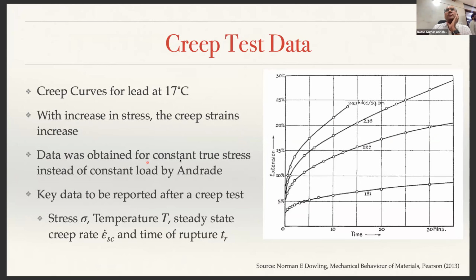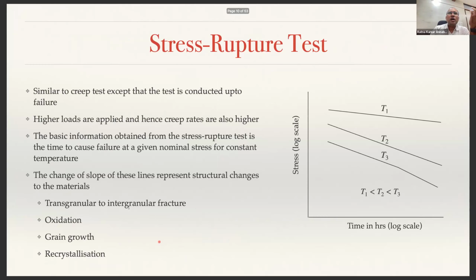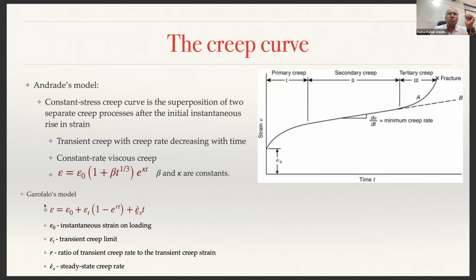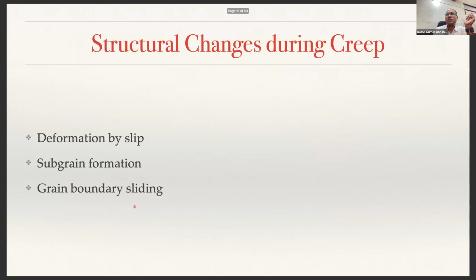Okay, so the key data to be reported after a creep test is basically the stress sigma, temperature T, steady state creep rate, epsilon SC dot, and time of rupture. These are the typical properties that you need in order to put them in the appropriate formula. For example, if you are using Garofalo's model, you need to know what is your epsilon SC dot that you will measure from the creep test.